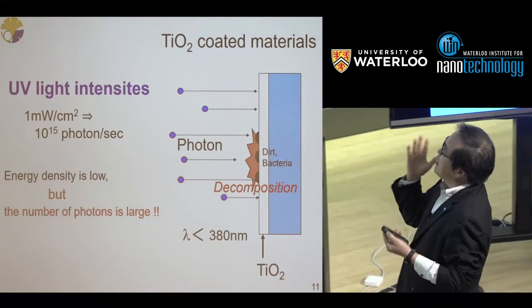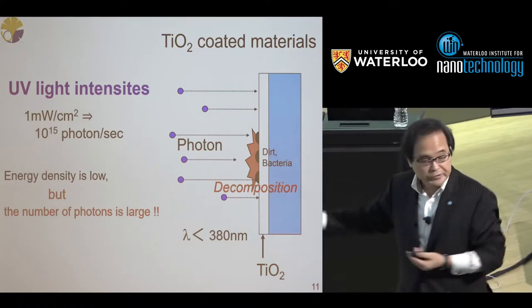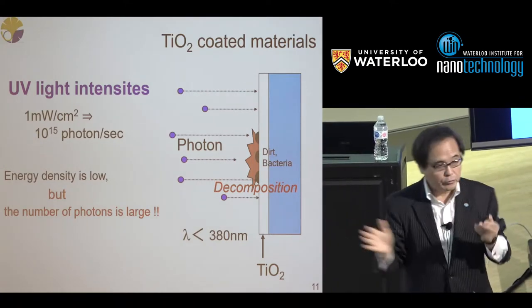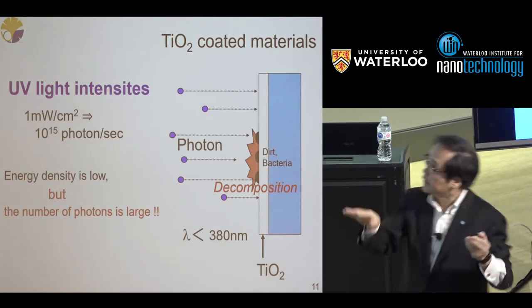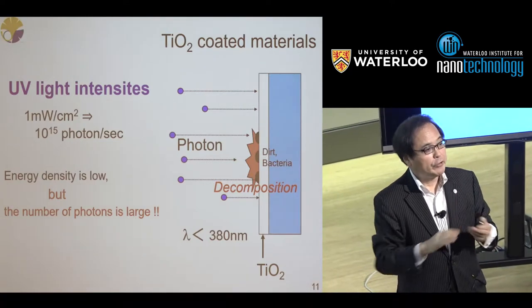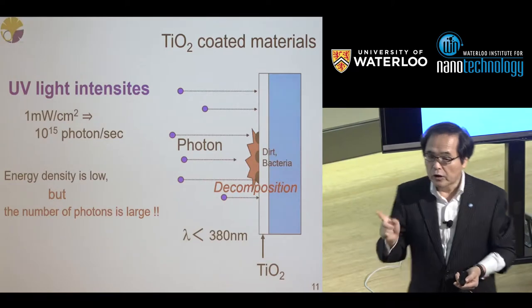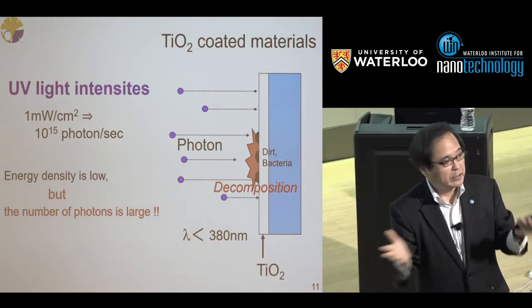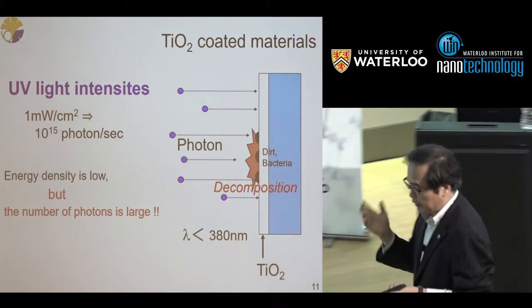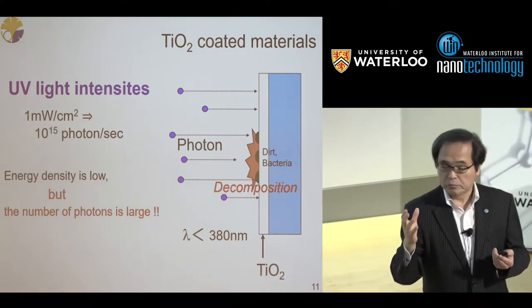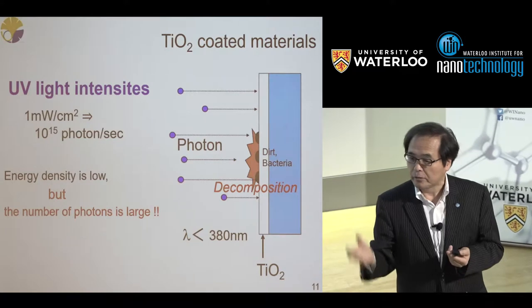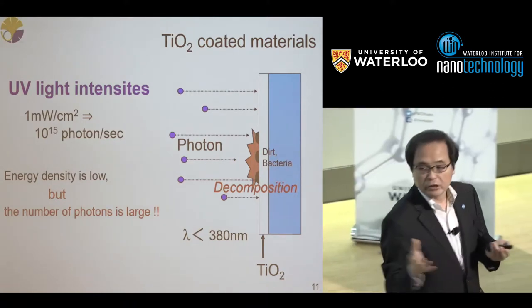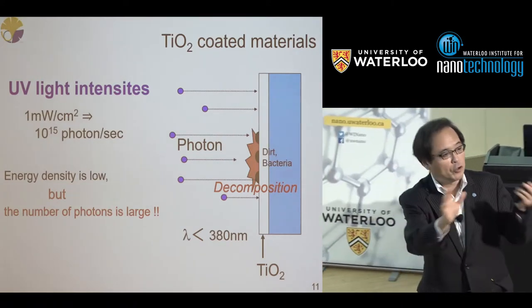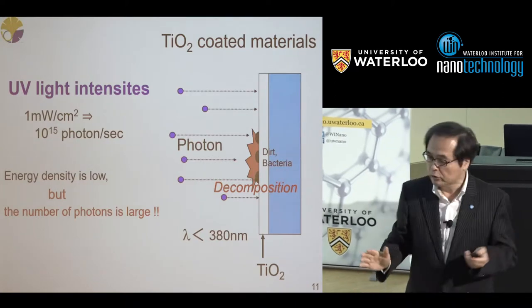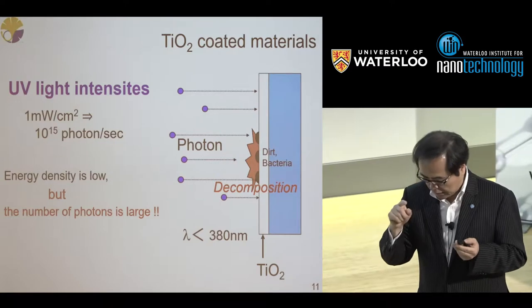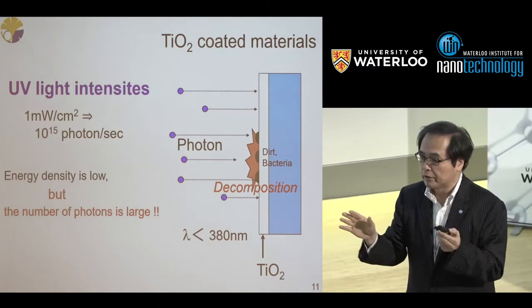So I got the idea that when we coat various things and illuminate with very weak UV light, some dirt or bacteria will be decomposed, even without irradiation of strong UV light. So the idea was to coat various substrates with titanium dioxide. But it was not so easy, because titanium dioxide has such strong oxidation power that the conventional organic binder will be easily decomposed by the photocatalytic reaction. That's why we have to have an inorganic binder, and depending on the substrate, we have to control the composition of the binder. So from the technological point of view, the development of the binder is very difficult and very important.